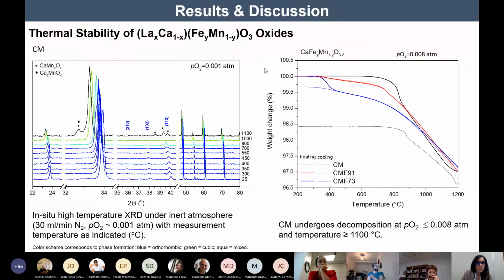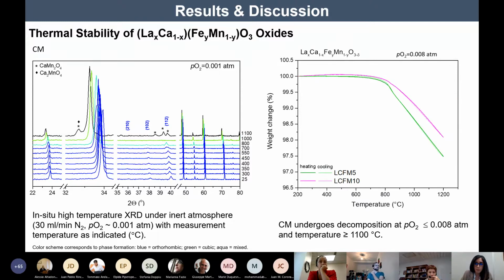I'm going to briefly show you some results. We first checked the stability of the materials. The calcium manganese oxide showed decomposition into Ruddlesden-Popper and spinel structures under the most reducing conditions that we used, both in the XRD and TGA analysis, in which the mass was not able to be uptaken back. All the doped compositions, with the exception of the 30% iron doped composition, were perfectly able to uptake back the mass, as you can see from these graphs, under the most reducing conditions studied.